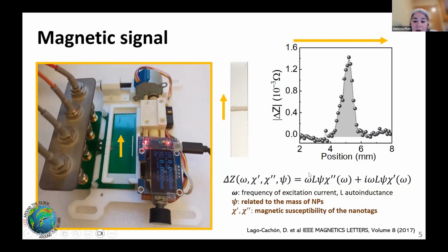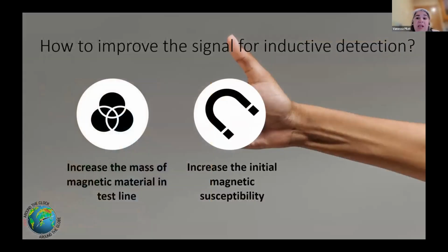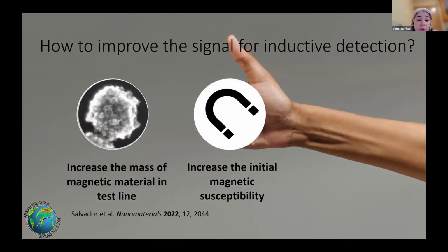This is proportional to several things from the sensor, but here I am focusing on the nanoparticle, the nanotag in the test line. It is proportional to the mass of nanoparticles. Of course, if we have more nanoparticles in the test line, we will achieve a larger signal. But this also depends on the magnetic susceptibility of the nanotags. We can improve the signal for inductive detection by increasing the mass of magnetic material. This can be achieved, for example, using magnetic clusters, but we can also increase the initial magnetic susceptibility by optimizing these nanoparticles. In my work, we are focusing on this part.